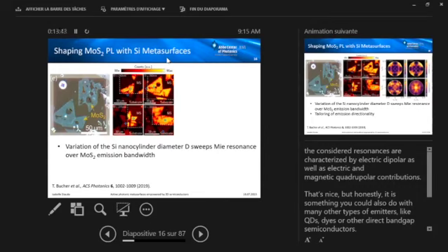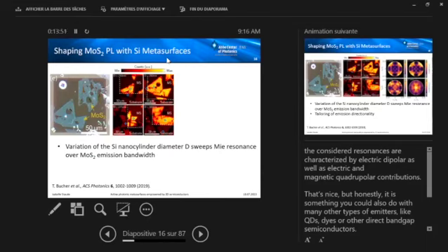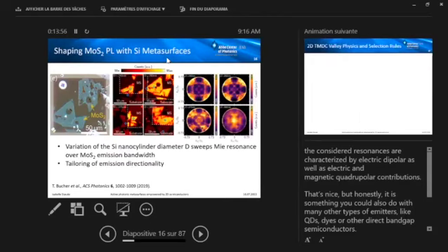And if you look at the emission properties of this coupled system, okay, hooray, we could see some enhancement, but we have to be careful, actually, to a very small degree, photonic enhancement. It's mainly because we're comparing the freestanding nature of the MoS2 on the metasurface with the TMDC on the substrate, where some substrate-induced quenching occurs. But what can the metasurface do?